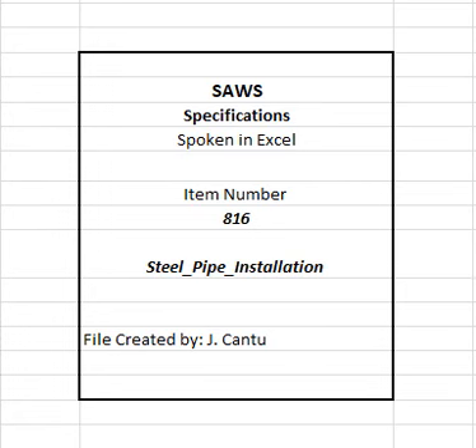22. Leaks in welds shall be repaired by chipping out the defective material and re-welded. No hammering will be permitted. 23. All steel pipe, bends, and specials shall be prepared, primed, painted, or wrapped in the field as specified herein. A. Exterior surfaces above ground.